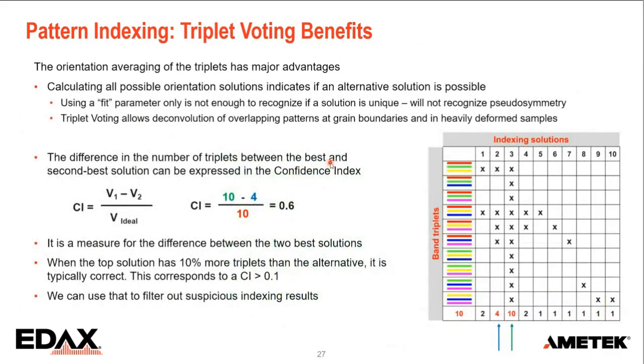Now, another benefit is, as I just mentioned, we know when there is a second possibility that's as good. When you would just use a fit or an angle parameter, it will not help you there, because if you have 2 solutions that are very similar, they will have the same fit parameter. So you cannot tell them apart, okay, this one's better than that one. But it also won't tell you typically that they are very similar, so you don't know if it's reliable. So what we do here, we know for each different orientation how many votes we have, and we can just look at the difference: the number of votes for the best minus the number of votes for the second best solution, divided by the maximum it could have got. And in this case, it's 0.6.